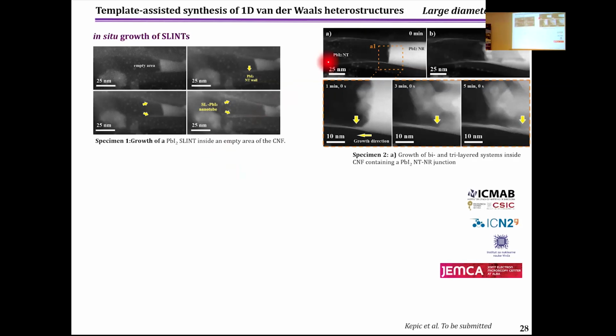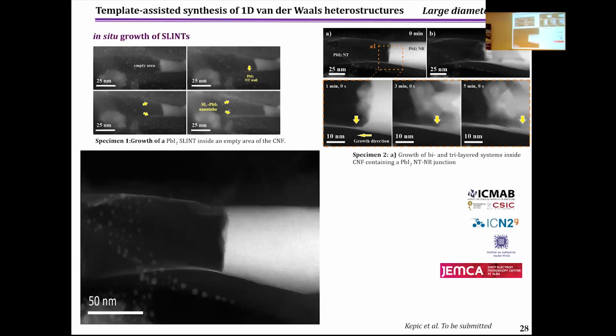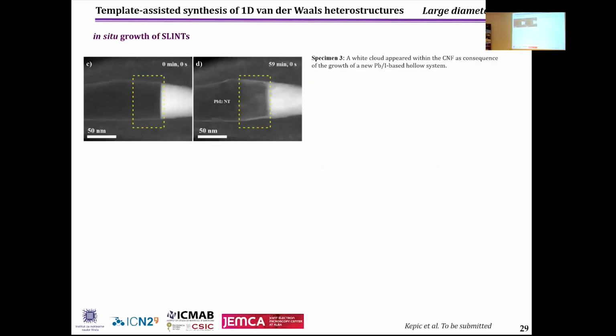In this case, we saw that we have junctions, namely one nanorod aside to a nanotube. We see that under the E-beam, under different energies, the rod practically dissolves or evaporates. And we can observe the creation of single-layer, multi-layer, bilayer, and also triple-layer nanotubes inside. So the electron beam has an effect on the formation of these nanostructures. This is a video, and we can see, sorry.